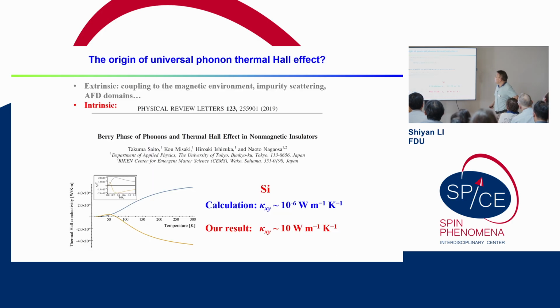But the final question is how to explain it: the origin of the universal phonon thermal Hall. Because for this high purity silicon, you cannot explain it with any impurity, domain, or magnetic environment, right? So it must be some intrinsic mechanism. But Professor Nagaosa did the calculation with the traditional ideas to calculate the Berry phase of phonons and gave a very, very small magnitude. Our result may be 6 or 7 orders larger.